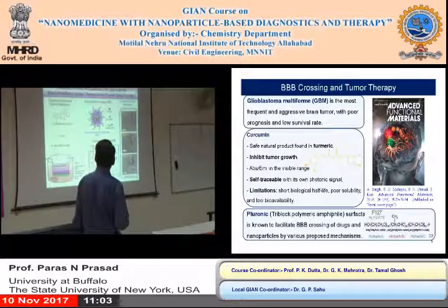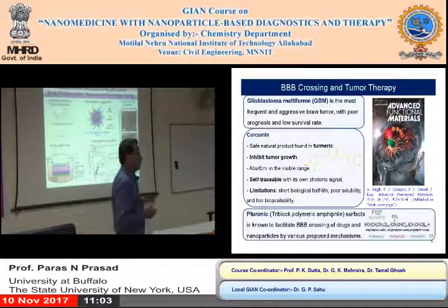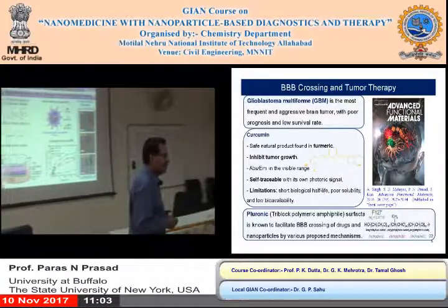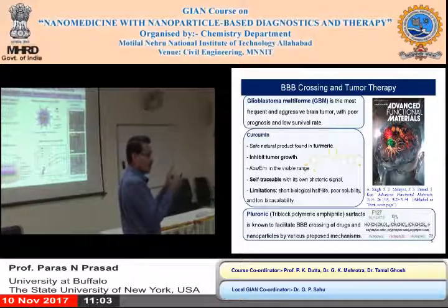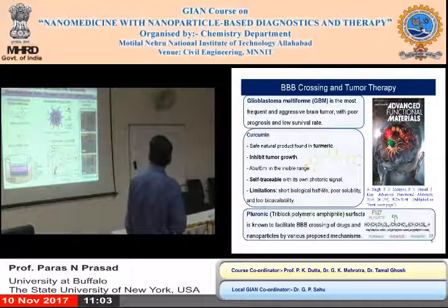And so we've made a nanoparticle that has curcumin trapped inside this pluronic polymer, which has the tails coming out, and these tails at the end have a charge. Okay, and then we encapsulated another dye that absorbs at the same wavelength where turmeric emits, so that there is energy transfer from curcumin to this dye. And this dye emits in the near infrared.